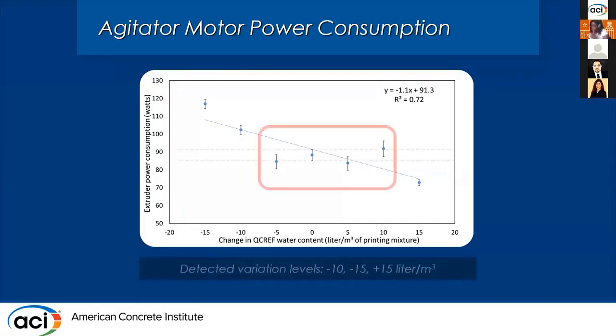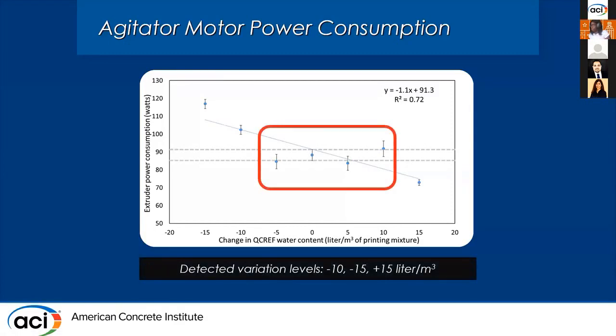And other than that general trend, you can see that in the range of -5 to +10 liter per cubic meter, we cannot really see any change. We cannot see any statistically meaningful change in the extruder power consumption. So basically this technique is not able to differentiate between these 4 levels of water content in the printing material.